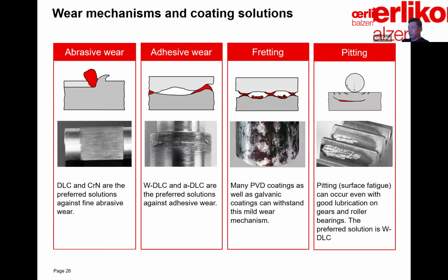especially for the primary wear modes, there are so many different kinds, like abrasive wear caused by hard particles, adhesive wear from metal to metal contact, and fretting and pitting. You can see all these types of wear in the field, but the good news is many PVD coatings can provide protection against these wear modes. And they reduce the friction and extend the life of the components.